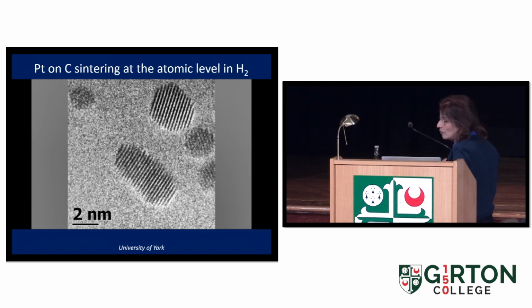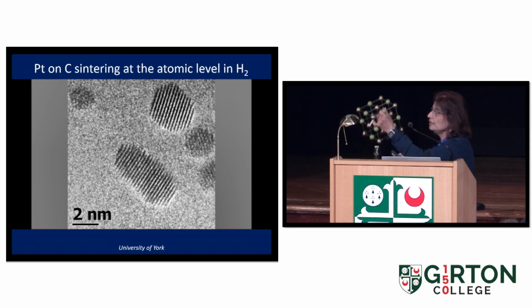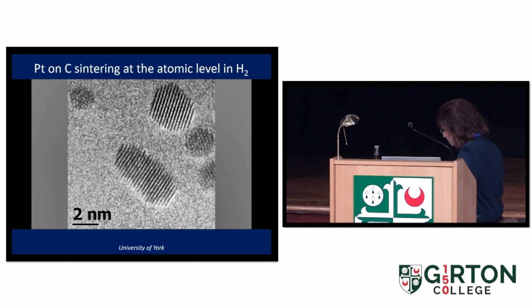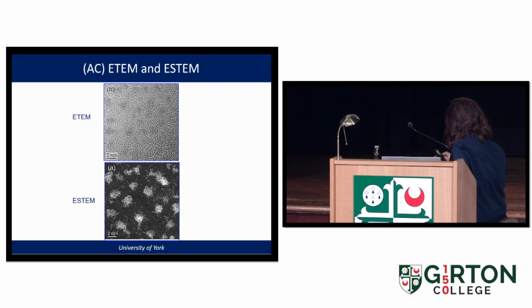This kind of tells us which actually planes are also involved in the reaction. There's this plane, that plane, and that's very important for us to understand and optimize the process. So for the first time, we have been able to look at these things at the atomic level. As I mentioned, in our instrument we have both transmission and the scanning. And in the E-STEM, we basically have square of the atomic number. So if you have platinum on carbon, platinum looks really bright on a carbon support. And you can see here, it looks like beautiful stars in the sky.